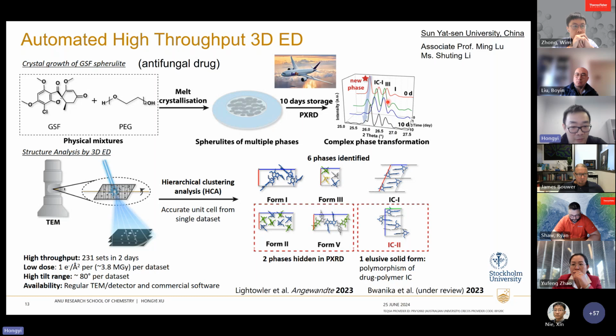And then we thought it's a perfect sample for testing a high throughput protocol we've been working on. So our group is developing software to do high throughput MicroED, fully automated, and at the same time, Thermo Fisher has EPU-D. So this work was actually done with EPU-D, but with manual crystal picking, and each crystal was diffracted over 80 degrees of tilt.